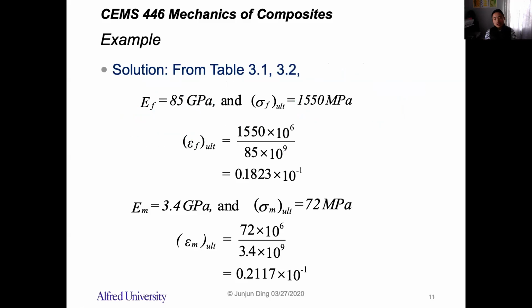Okay, so first of all, you want to calculate the ultimate strain of the fiber and the ultimate strain of the matrix to see which one is larger, because we know the Young's modulus of the fiber, the Young's modulus of the matrix, and the ultimate stress of the fiber and the matrix. Then you can find the ultimate strain of the fiber and of the matrix, right? You see the ultimate strain of the fiber is lower than the ultimate strain of the matrix. That means the fiber will fail first, right? So the ultimate strain of the composite will be equal to the ultimate strain of the fiber, right?